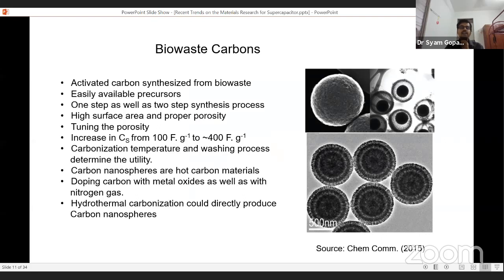And usually with activated carbon, using chemical activation or physical activation, the carbons we get will have a higher surface area as well as proper porosity. And in this bio-waste carbon, the basic research for supercapacitor application will be tuning its porosity. That means the correct porous structure is required for this material to have proper intercalation with electrolyte ions.